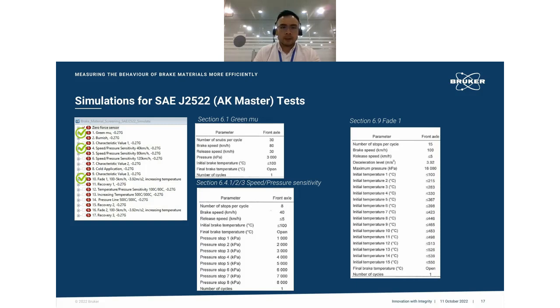In our studies, we actually simulated the entire flow of the SAE J2522, which is the AK master test. So I took out a few of the test conditions or test parameters that have been extracted from the AK master standard. This is what we actually mimic, through different contact pressures, where we vary the load applied onto the disc, as well as making use of the heater to perform a fade test at various temperatures required, from 100 all the way up to 550 degrees Celsius.